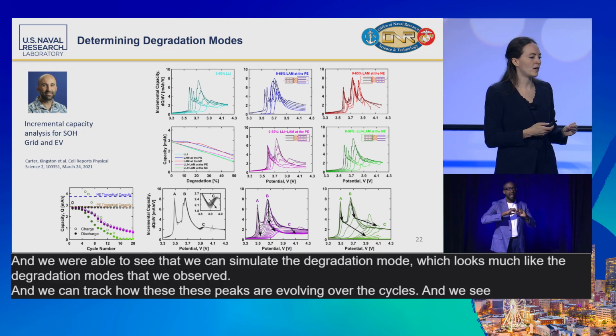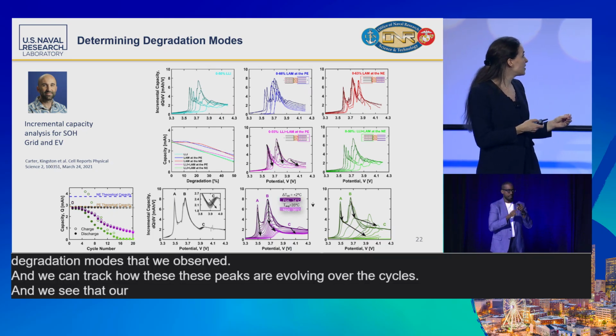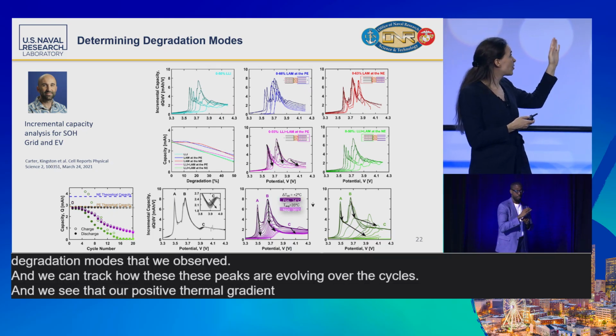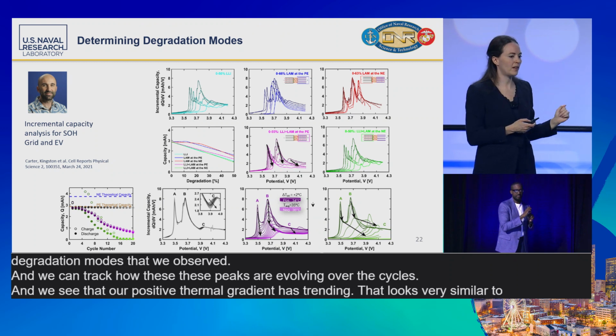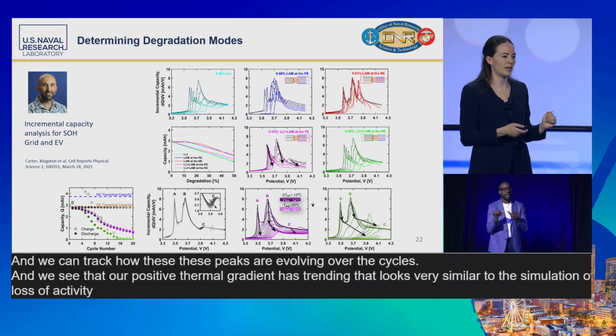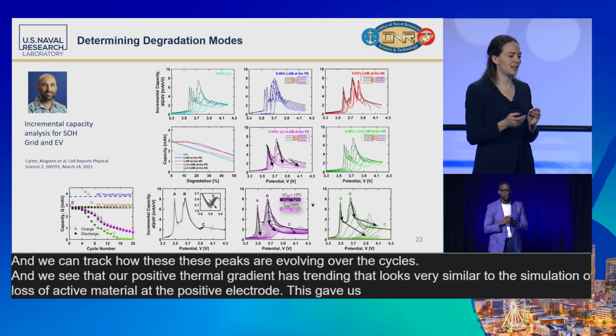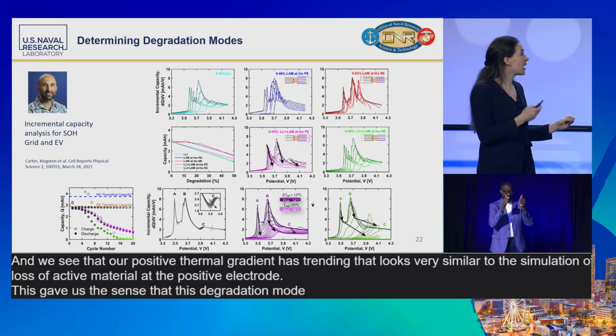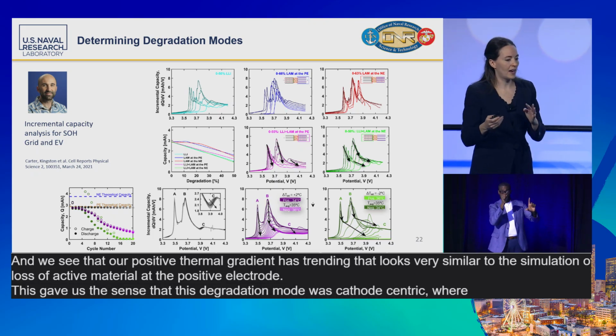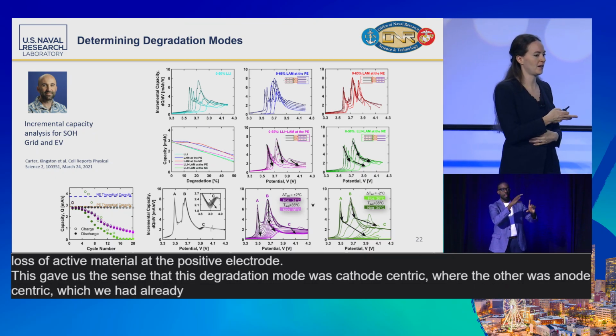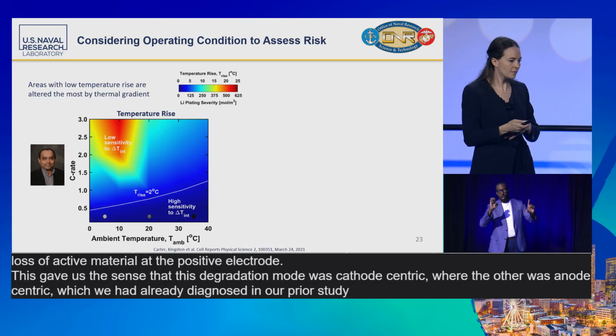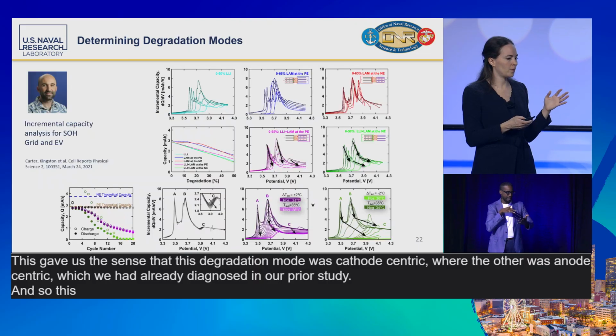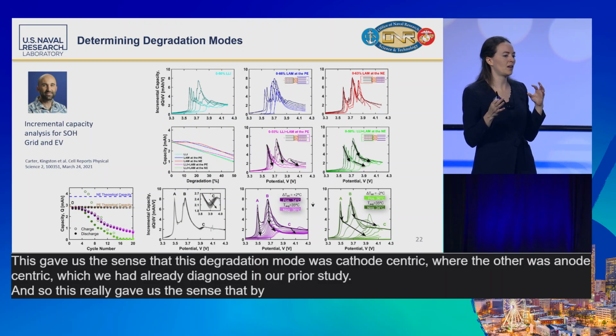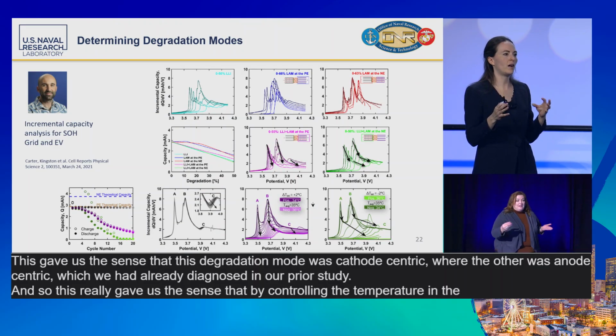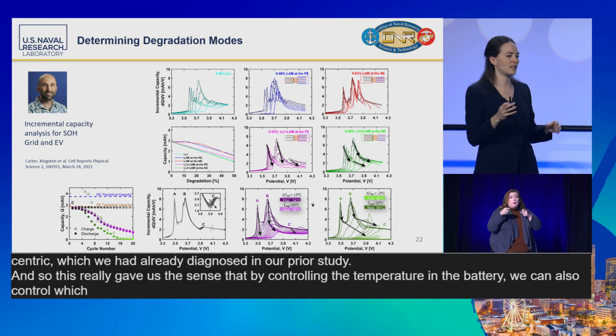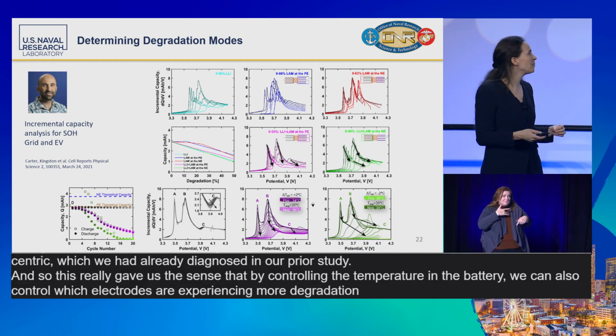We see that our positive thermal gradient has trending that looks very similar to the simulation of loss of active material at the positive electrode. This gave us the sense that this degradation mode was cathode-centric, where the other was anode-centric, which we had already diagnosed in our prior study. And so this really gave us the sense that by controlling the temperature in the battery, we can also control which electrodes are experiencing more degradation over time.